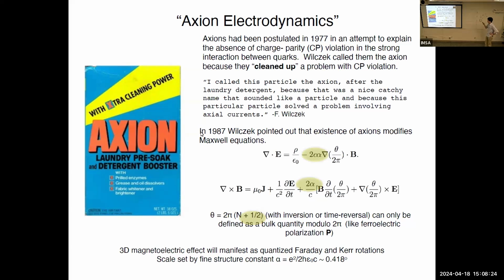What I want you to pay attention to is that it has this delta gradient term here as well, which means that this effect is only observable at the interface between two media which have different axion angles. So which means that although we consider TIs to be just magnetoelectrics, this formulation already gives you an effect of a surface state, because the only effect you're going to see in the TIs is going to be on the surface, and this gradient basically shows that.